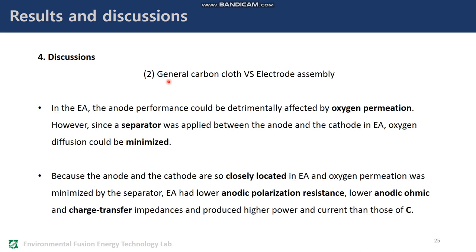And then, we also compared general carbon cloth anode and electrode assembly. In the EA, the anode performance could be detrimentally affected by oxygen permeation. However, since a separator was applied between the anode and the cathode in EA, oxygen diffusion could be minimized. Because the anode and the cathode are so closely located in EA and oxygen permeation was minimized by the separator, EA had lower anodic polarization resistance, lower anodic ohmic and charge transfer impedances, and produced higher power and current than those of C.